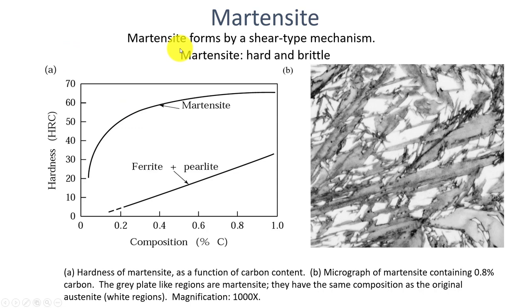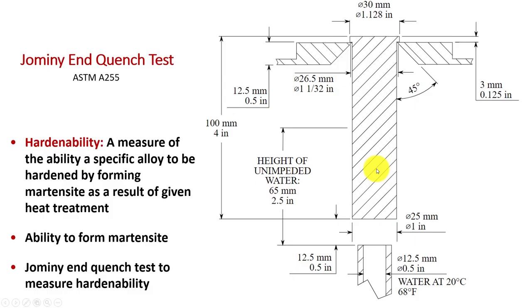What is martensite? It is formed by a shear mechanism where we're trying to go from FCC to BCC, but it becomes body centered tetragonal — BCT. Metallurgists refer to this as white feathery structures. This is what martensite zoomed in heavily would look like on a microscope. We're going to be testing the hardenability in this lab — it's basically the measure of the hardenability of an alloy forming that martensite. We're going to see how well different alloys based on carbon and alloy compositions produce martensite.